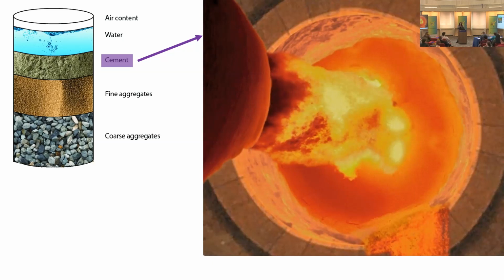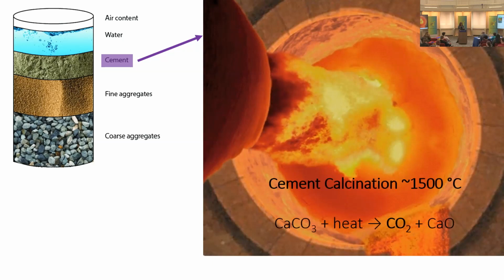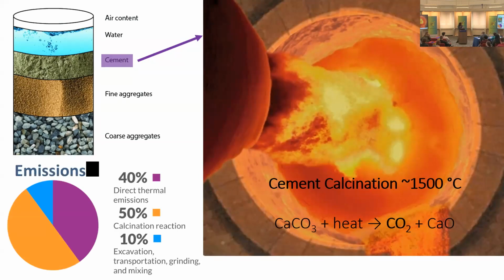And it's in this process where 90% of the emissions from cement come from. 50% are from the reaction called calcination, where the calcium carbonate, or limestone, turns to calcium oxide, and in the process, carbon dioxide is released. And the 40% is from the exorbitant amount of energy we need to create this much heat. The other 10% is from the excavation, transportation, grinding, and mixing processes. The industry standard cement is called Portland cement, and the most common is called ordinary Portland cement, commonly referred to as OPC, which I'll talk about from here on out.